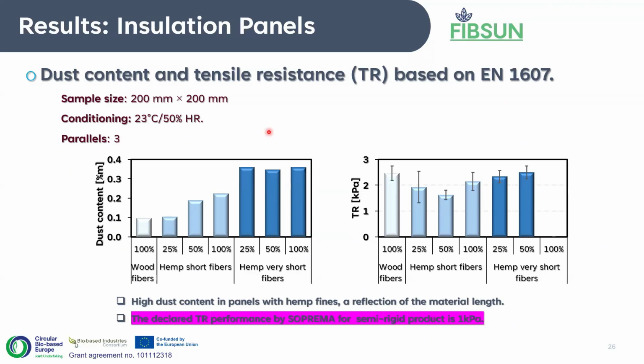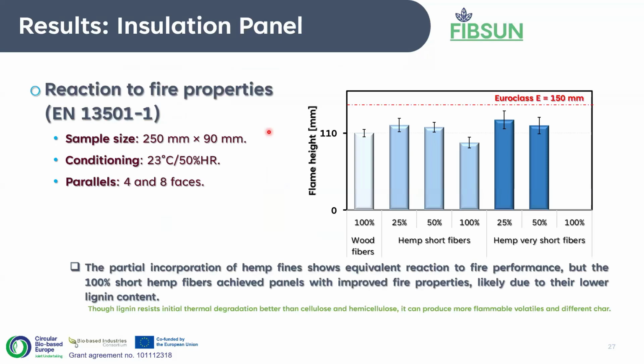Then we also investigated the tensile properties, in this case, perpendicular to the surface of the boards. And of course, we see that the wood tensile properties are quite higher compared to the hemp biomass. But of course, we relate these first to the interaction between the wood and the binder, and of course, the size of the wood fibers. And then we try to understand what is the reaction to fire properties of the panel.